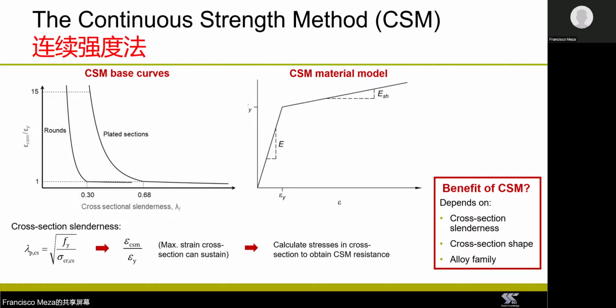So how much you can benefit from the CSM will depend on a few factors. The more compact the cross-section is, the greater the resistance you will get due to strain hardening. Also, the shape of the cross-section and the alloy family will condition how much benefit you get from the continuous strength method. So, for example, austenitic stainless steels will benefit more than duplex stainless steels because of their superior strain hardening.